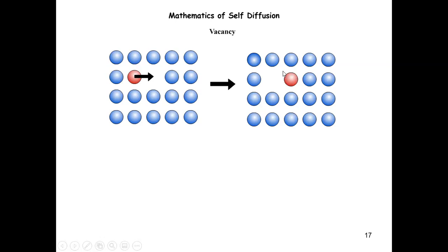So in the last lecture, we considered the ideal case that if the crystal structure or the material is a perfect crystal, okay? It's a perfect single crystalline material. It might be very small in size, but in principle, we can make it a perfect crystal. And we know that there will be no diffusion in that system. There's no substitutional diffusion, right? Because there's no vacancy for any atom to move into, so there will be no transport of atoms in this particular scenario, right? So a necessary condition for substitutional diffusion is that you have to have a certain concentration of vacancy.